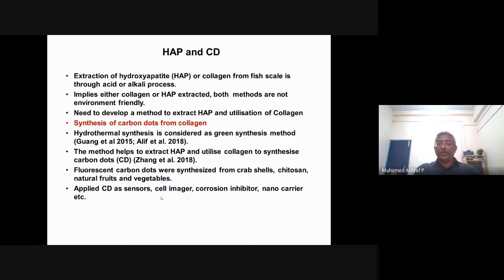So what we thought is that we can use a hydrothermal reaction to extract and convert this collagen into a carbon dot. It is a nanomaterial, and hydroxyapatite can also be extracted in nano form. So we standardized a procedure for extracting nano carbon dots and hydroxyapatite, and beta tricalcium phosphate also.